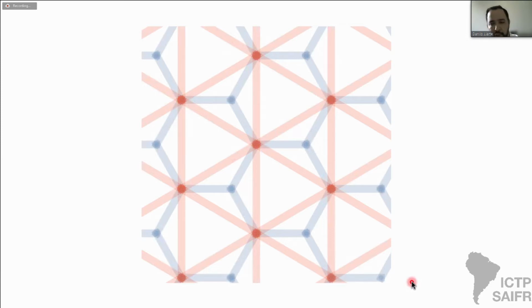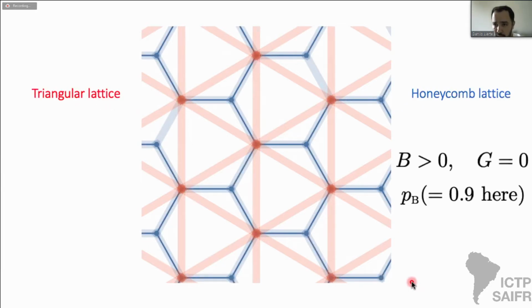What you have here is a combination of two lattices, the honeycomb lattice in blue and the triangular lattice in red. The honeycomb lattice has a finite bulk modulus and a zero shear modulus. That means that it resists changes in volume, but not shear deformations. I'm populating each bond of this lattice with probability PB, which I take to be 0.9 in this figure. And just to be clear, what I mean by bond is just a harmonic elastic interaction, a spring.